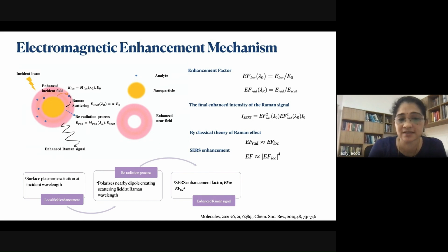Surface plasmon gets excited at the incident wavelength, and local field enhancement happens. And the polarized dipole creating a scattered field at the Raman wavelength causes a re-radiation process. They combine together to produce a SERS enhancement factor of EF, that is, the enhancement factor raised to 4.